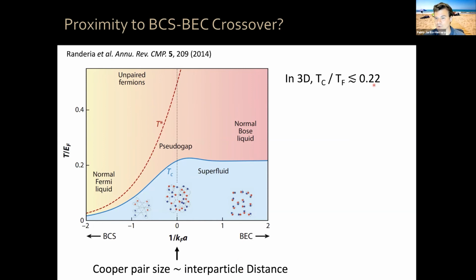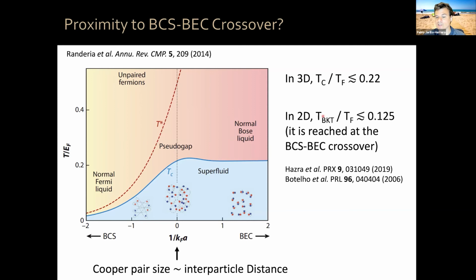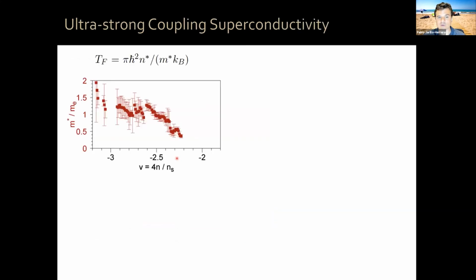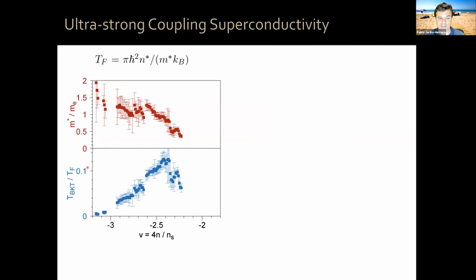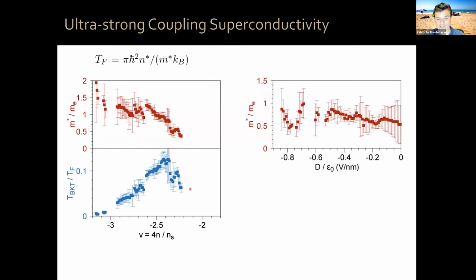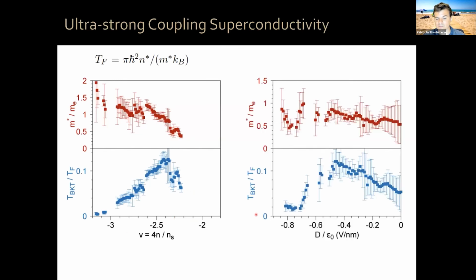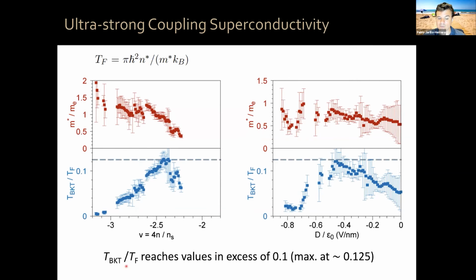In 3D, there's a bound of 0.22 for this. In 2D, T_BKT over T_F is bounded by 0.125, which is reached at the BCS to BEC crossover. Because we can measure the Fermi temperature and T_BKT in our system, we can study this as a function of displacement field or filling factor. You can see that we actually reach T_BKT over T_F values in excess of 0.1, with a maximum at 0.125.